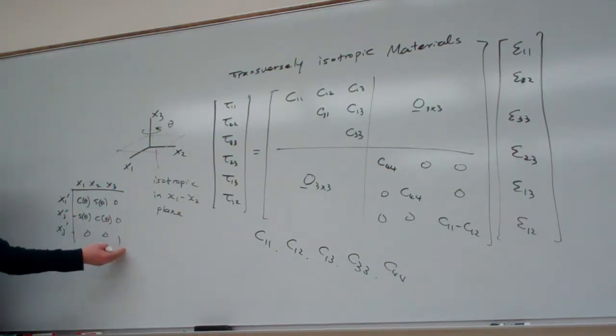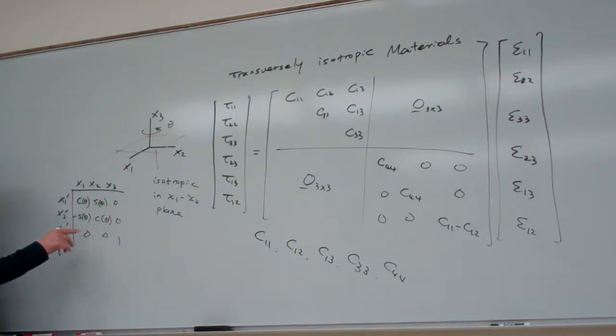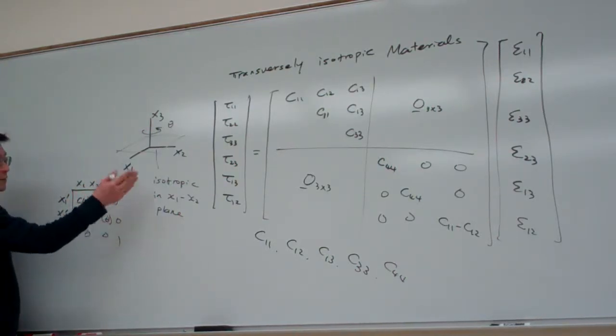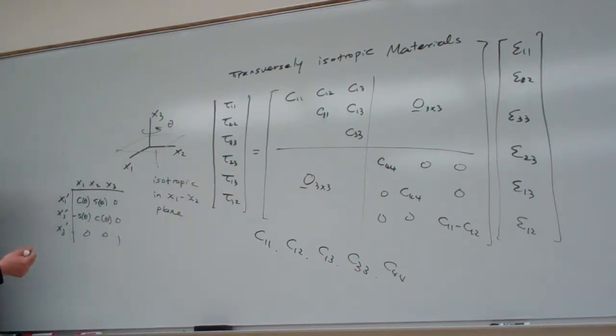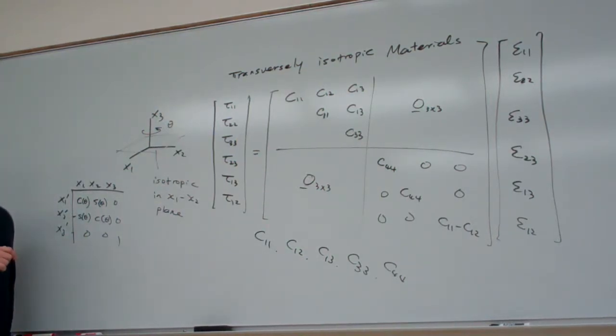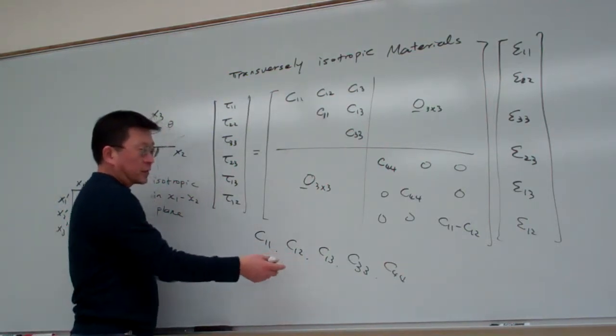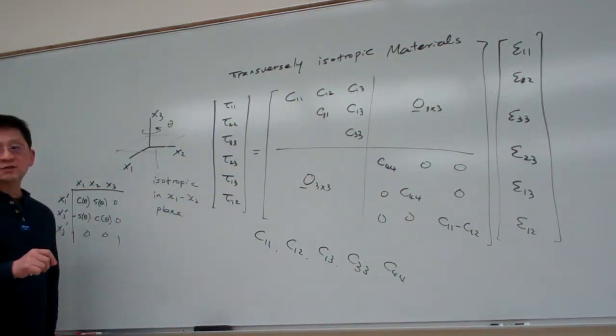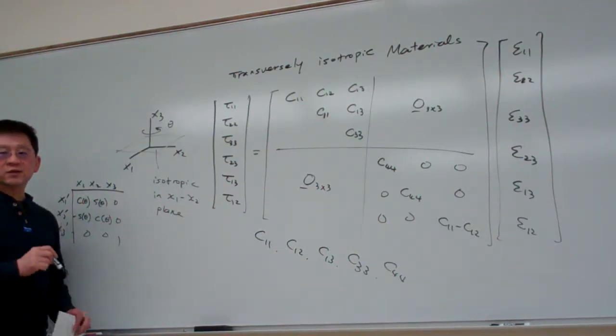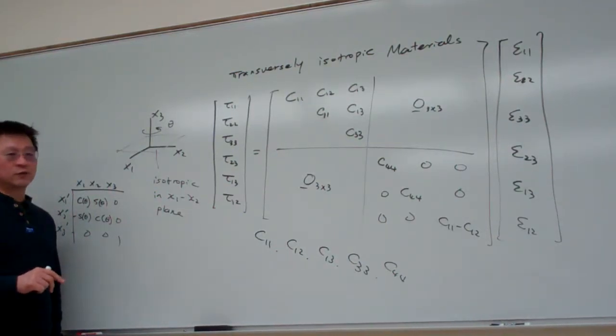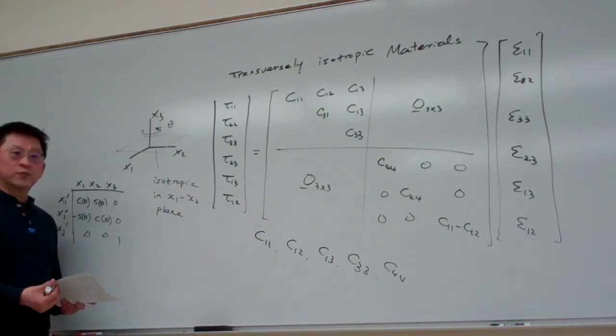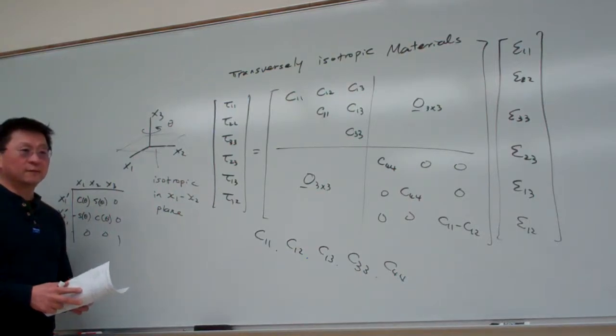I have applied such a transformation matrix, and then in the remaining process, I claim for any number of the theta, the material properties must be the same, doesn't matter how, regardless of the change of the theta. So stick with this requirement, and then remaining process in showing in the handout is this. We knock out all the elastic constant that associate with the theta. Those constant must be zero.